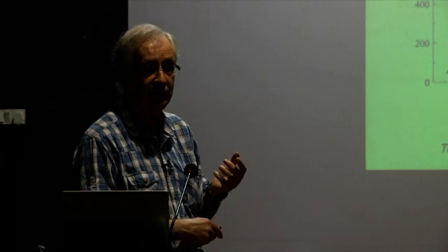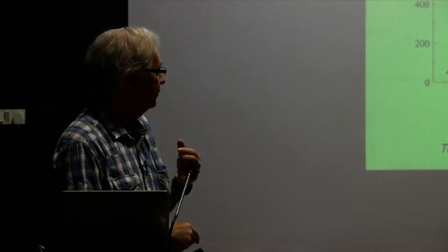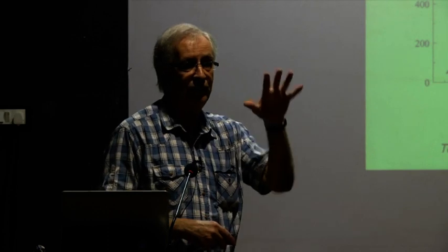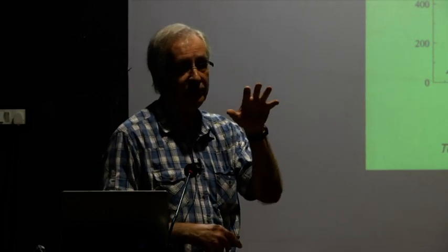So here you consider the S and D electrons. Those make up the valence electrons, and here they're the S and P electrons. And then what you do is you just take a weighted average. So you have 50%, that's 0.5 times 10, plus 0.25 times 7, again plus 0.25 times 3. You get 7.5 electrons per atom for that particular composition. Now, this is the number of valence electrons.